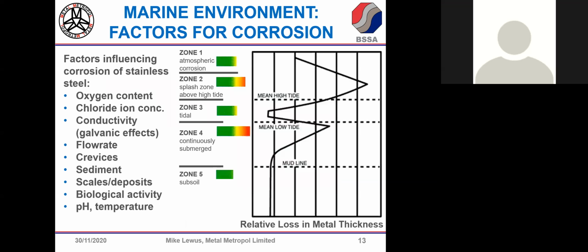And if I just go on to some data that's often shown to show the different levels of aggressivity in the marine environment. This is a curve. It shows the relative corrosion rate, or in this case, it's labelled relative loss in metal thickness, and it references harbour piling. But you'll see immediately there are a number of zones. The first one, zone 1, is the atmosphere. And you can see if we're high up in the atmosphere where there's less chloride dissolved in moisture, the corrosion rate is lower. As we come down to the splash zone, it increases.